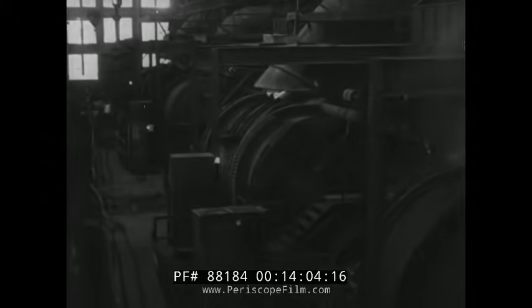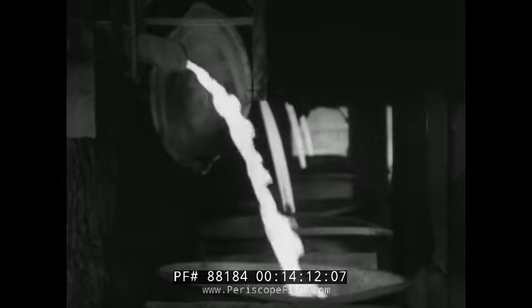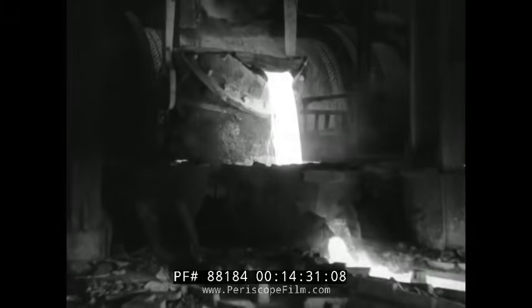The smelting plant at Coniston, located about 10 miles from Copper Cliff, employs a different type of ore treatment. A series of blast furnaces are charged with selected ore and suitable flux to produce a special quality matte. A battery of basic converters treats this matte until it has reached a very high metallic content. One product of this smelter is a special matte which is returned to Copper Cliff for separation into copper and nickel. The Coniston final product is about 20% sulfur and 80% metal, carrying a ratio of 2 parts nickel and 1 part copper. This matte is poured out into slabs, broken up and shipped to the Huntington, West Virginia plant for the production of Monel.